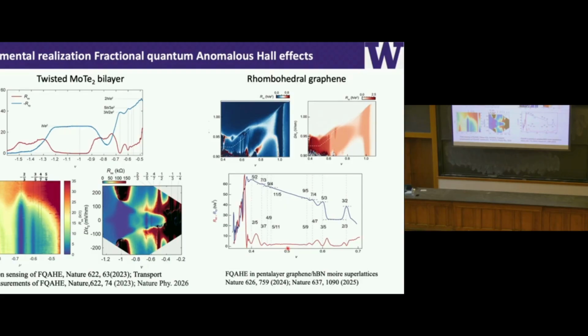Graphene is a semimetal. What semimetal means is that it's easy to make a contact. So once you have a good contact, you can observe, for example, fractional states at small fillings, below 1/2. These low filling states are difficult to access in our semiconducting systems. So in transport, we actually don't observe these low filling states. We can use different techniques, but not transport.